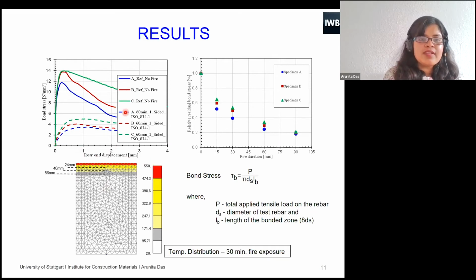These are the numerical results. You can see for this around 12 to 14 MPa strength we are getting, whereas even after 60 minutes of fire, that is 1 hour of fire, the bond strength has reduced a lot. You can basically see the bond stress percentage. Even after 15 minutes of fire, the bond strength has decreased to 60%. That means the impact on bond stress is really huge.